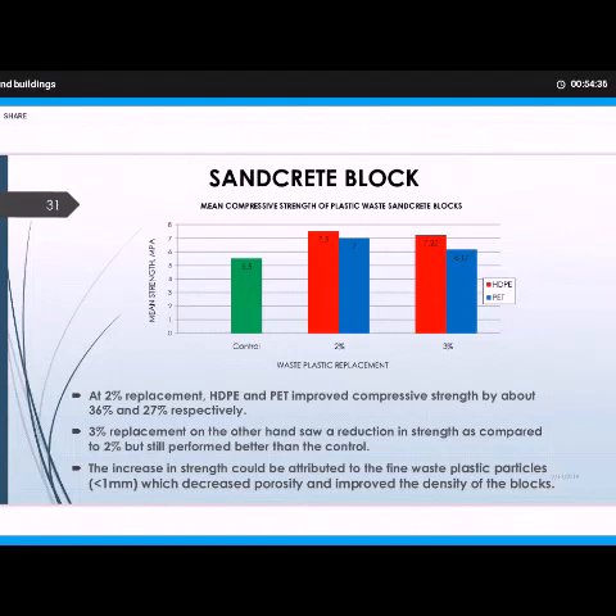Now, per the analysis, it could be said that this is because of the fine nature of the plastic we used for the plastic block. The plastic waste that was used was less than 1 mm, which is sometimes even finer than the sand that is used. And so we believe that because of its fineness, it is able to fill the pores, thereby making it more consolidated and more dense and increasing the strength.